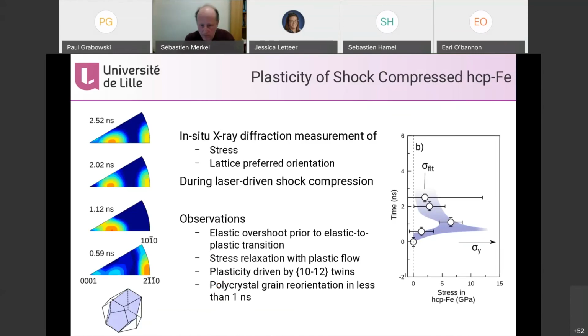We're looking at the average properties, but still, with observations of a big elastic overshoot prior to the elastic to plastic transition, and stress relaxation with plastic flow, which we see in some experiments, which is driven by 10-12 twins, and it happens in less than a nanosecond when it starts.